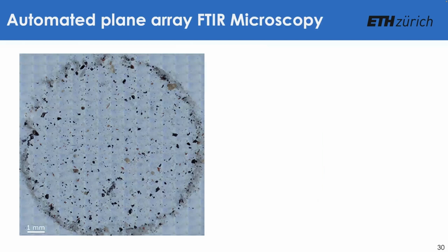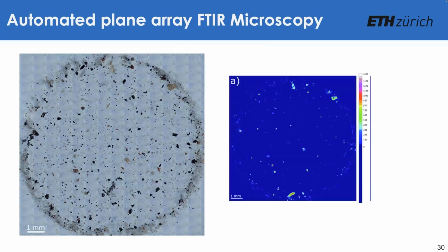to get. This is a typical microplastic sample that has already been purified using some extraction technique. There's a lot of particles there. Some of them might be microplastics and some not. So when this goes under the micro FTIR, you are able to start to see some of the particles which are more likely suspected to be plastics, because the beam is rastering over the entire sample and measuring particle by particle the chemical composition of this particle.